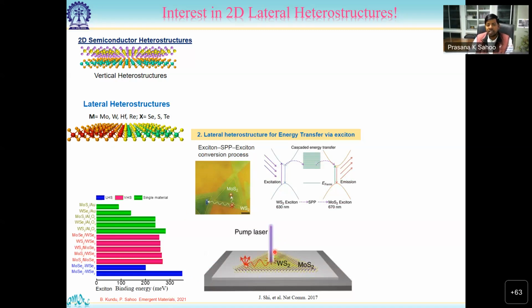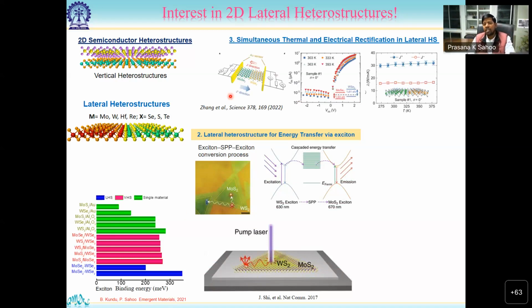Because of the lateral geometry, once you form excitons, they can be coupled with other energy sources like surface plasmons. They can be transported easily through these lateral dimensions. In terms of devices, when you make a 2D transistor or diode, you have to manage the thermal energy. Very recently, one group also showed that using lateral directions, it also acts like a thermal rectifier. In thermal management, the heat can flow in a certain direction more strongly than in the other. So simultaneous electrical and thermal rectification is also possible using this geometry.